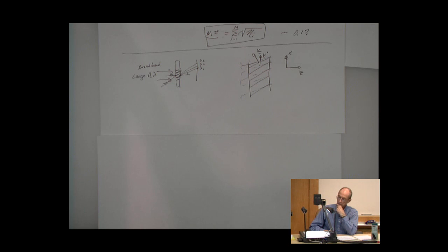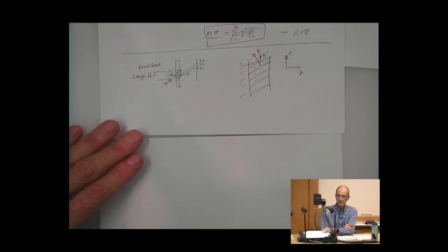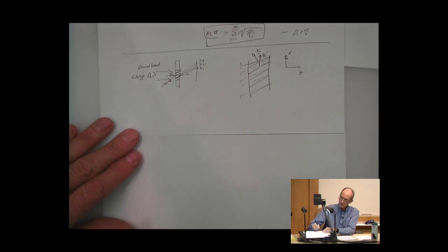So my first inclination was that if you swell, you're going to increase the wavelength that does the Bragg matching for this. Now that's always true for reflection holograms. However, for a transmission hologram, it can either decrease or increase depending upon which direction you reconstruct it at. So that was something that was a little surprising to me. I didn't think it would change for that. But let's look at that.